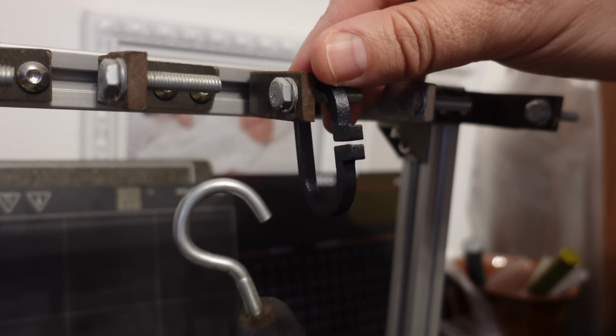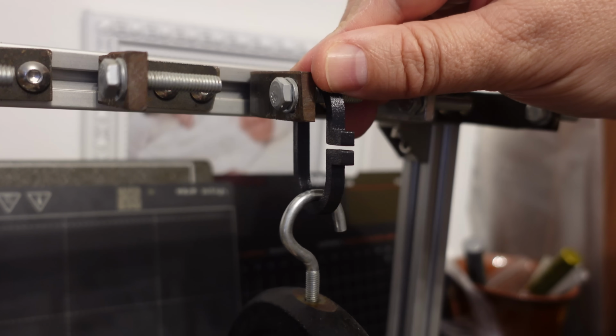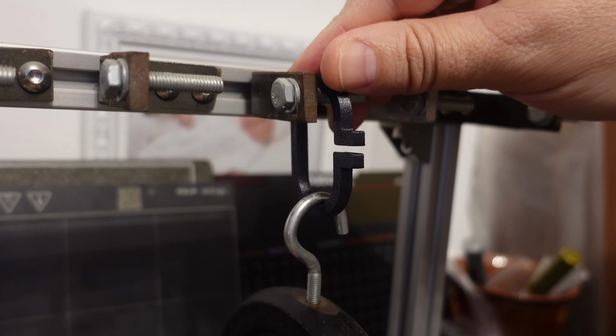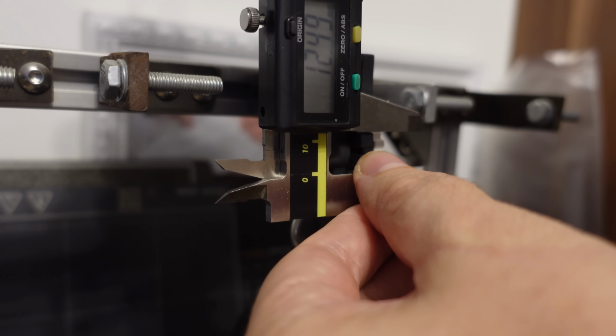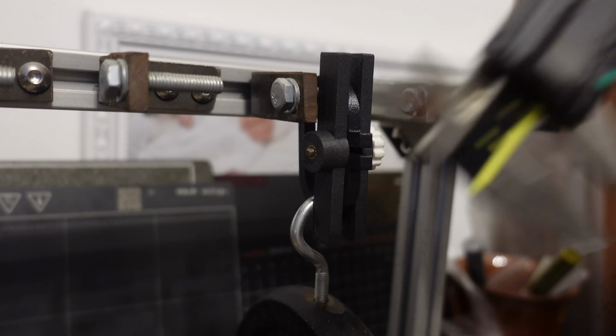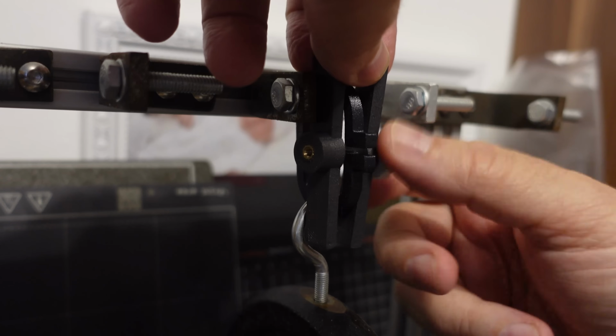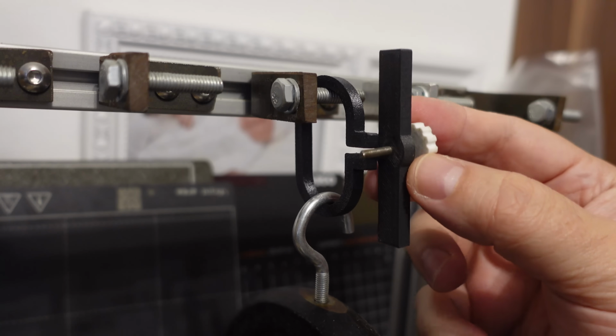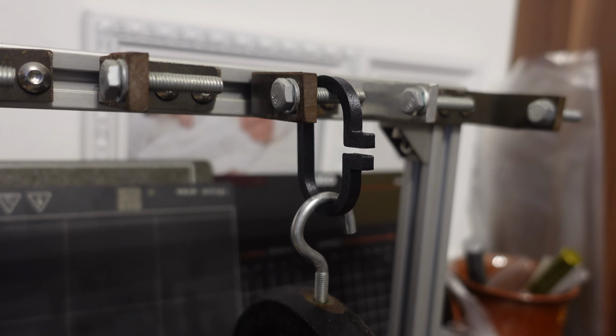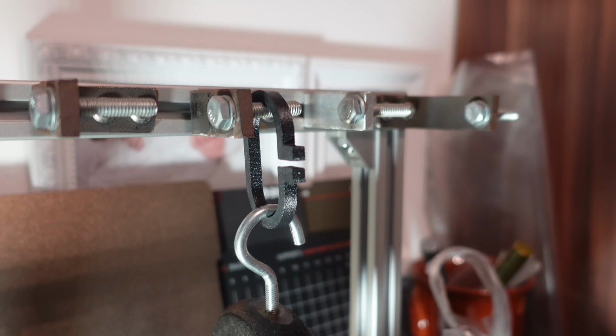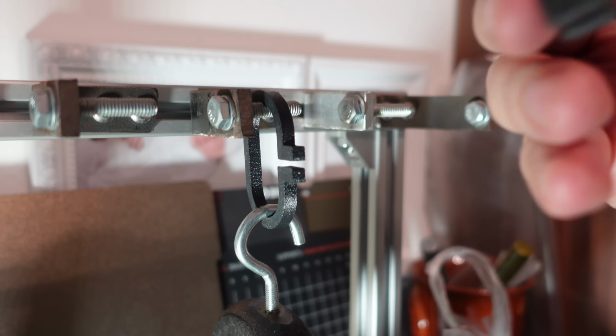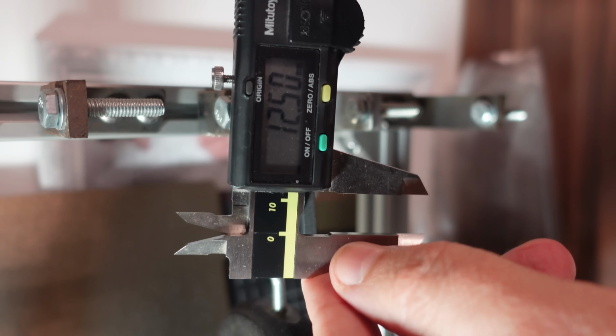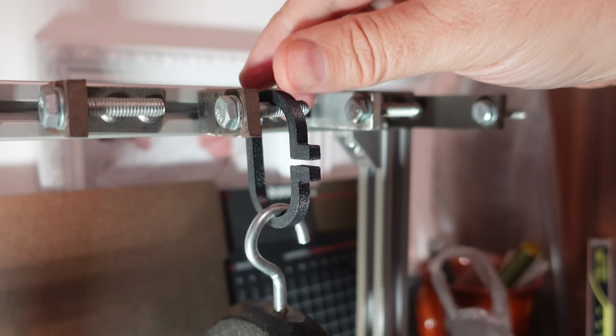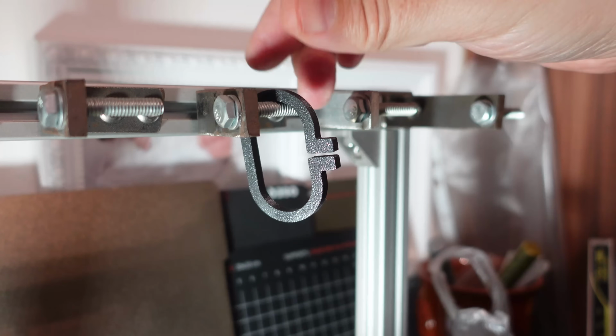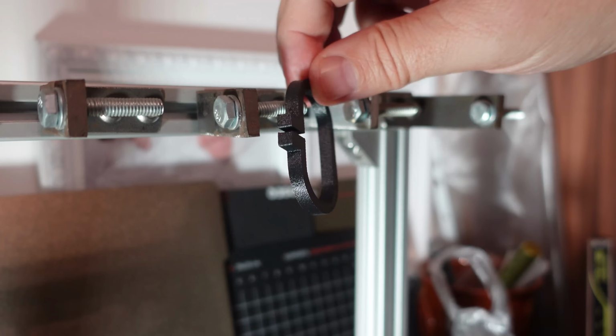Creep test, the deformation under a constant load of 1.25 kilograms. 12.49. The deformation is so small that I have to go around. Too small a gap for the bolt. This is the last day of the measuring, and I already know the result because even compared to day 0, there were absolutely no changes. Let me show it to you. 12.50. Visually no deformation on it at all.